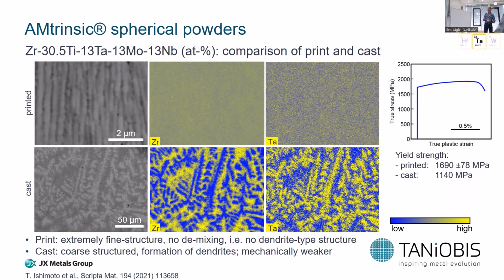But the main feature I want to point out is the difference in the cast structures, where you see this standard type segregation, and this is due to the low cooling rates, in comparison with the very high cooling rates of the additively manufactured samples, where we have an extremely homogeneous distribution of all constituting elements, here pointed out for zirconium and tantalum.